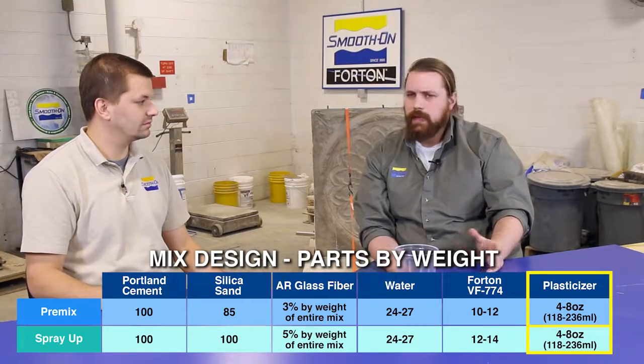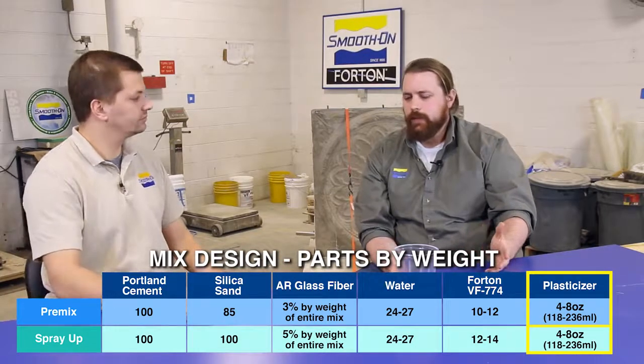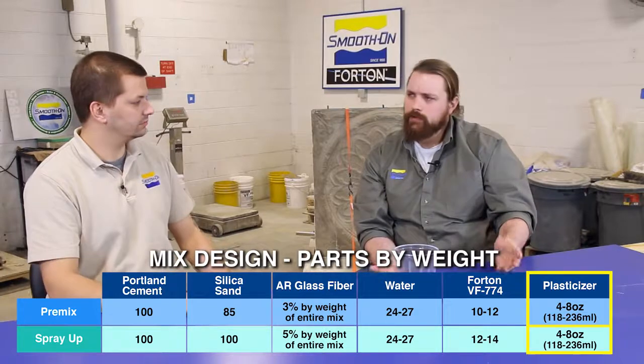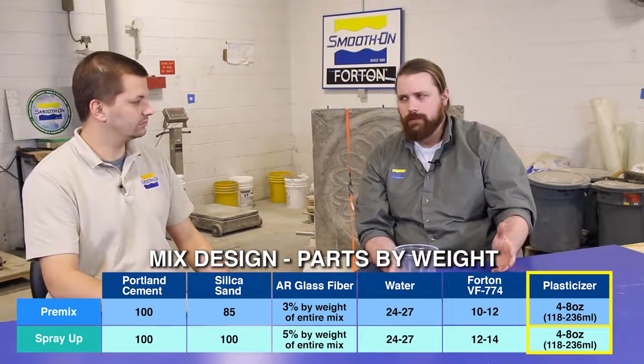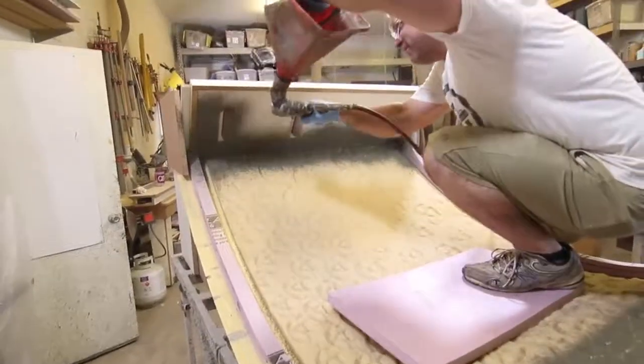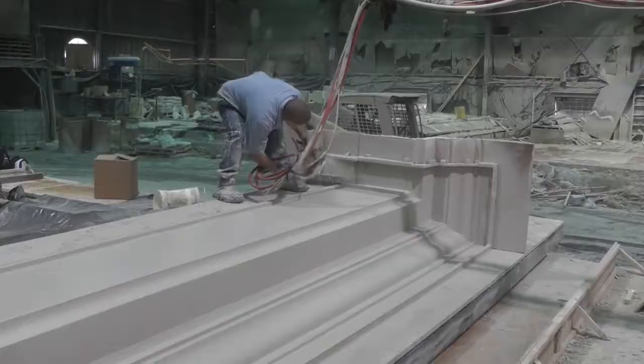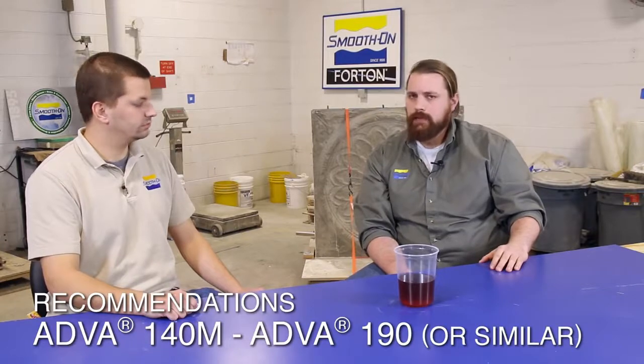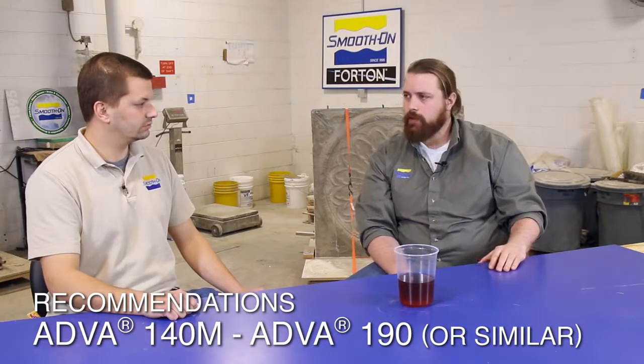Again, not a whole lot is added to a system though. You might be looking at between like 4 and 8 fluid ounces per 100 pounds of cement. So it's really not a lot, but it's very key when you're getting into the workability of the material and the sprayability of the material, for it to be able to move through a gun but still hold a vertical surface when you apply it onto your mold. So this is a pretty key component. We recommend some products from ADVA. The ADVA 140, ADVA 190 are good materials, and there's some others on the market as well.